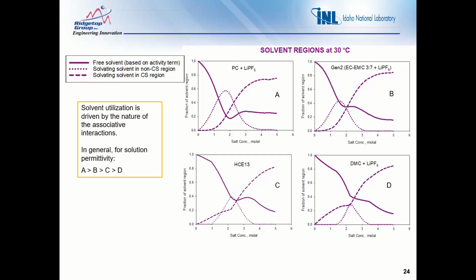As we start to add salt, we see that drops quickly, and then we have the solvating solvent in the non-aggregate, I would say single ion type solvating region, which is the dashed or dotted line. And then the heavy dashed line is the solvent engaged in the multidentate type bridging behaviors. So that tends to increase quite a bit as you go to the highest salt, whereas the free solvent tends to plateau a little bit in some cases, but still diminishing. And then the solvating solvent as applied to free single ions almost completely disappears in some cases. Okay, next slide.